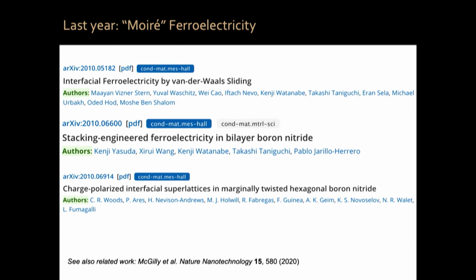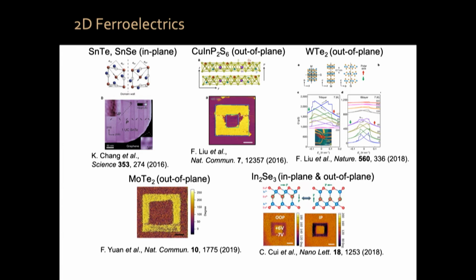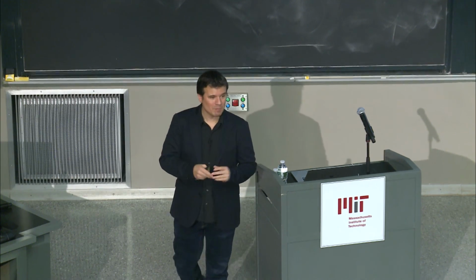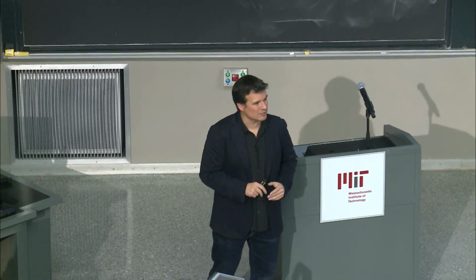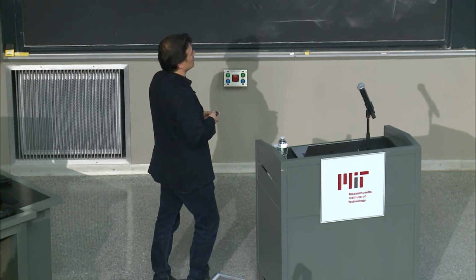Now, how is this ferroelectricity different? In general, ferroelectricity doesn't like 2 dimensions, okay? Many materials which are ferroelectric in 3 dimensions, if you make them 2-dimensional, the ferroelectricity disappears. That happens not only with ferroelectricity, but with any order. Ferromagnetism also doesn't like 2 dimensions, okay? You have a theorem that says that you cannot be ordered in 2 dimensions. Now, the theorem, of course, doesn't work because we have graphene and we have many other things that order in 2 dimensions, but it imposes restrictions on whether you can realize order in 2 dimensions.